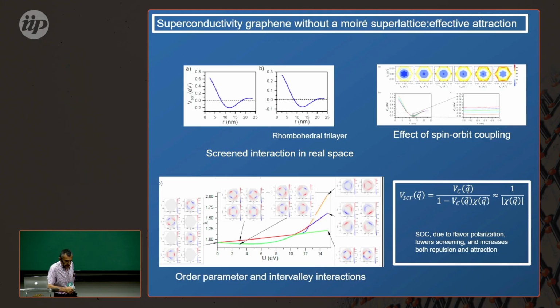So you can go back to real space, and this is the screen interaction in real space. As Kohn and Luttinger estimated—I mean, it's not exactly what we found, it's not exactly based on 2kF scattering because the Fermi surface is very deformed. But in any case, there are minima, and that is why you can have superconductivity.